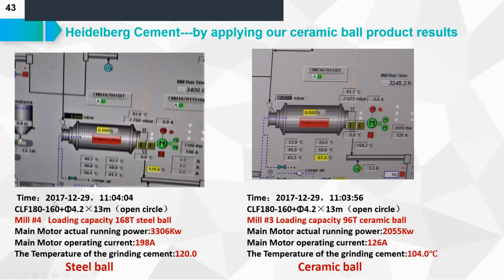Actually, Heidelberg gave us mill 4 and mill 3 to make a comparison test. Mill 4 is loaded with steel ball. In chamber 2, it's 168 ton of steel ball. And in mill 3, we are applying ceramic ball. We're loading about 96 ton. So it means nearly half we decrease of the loading.